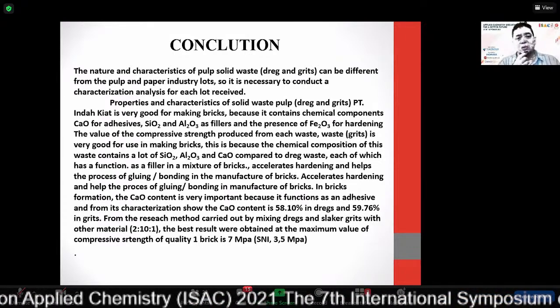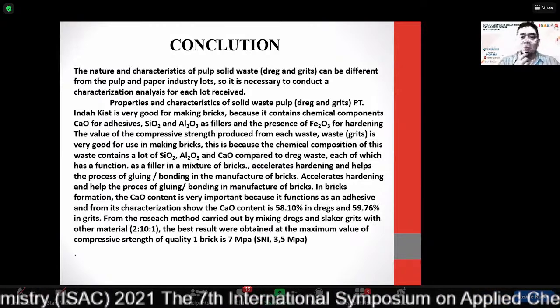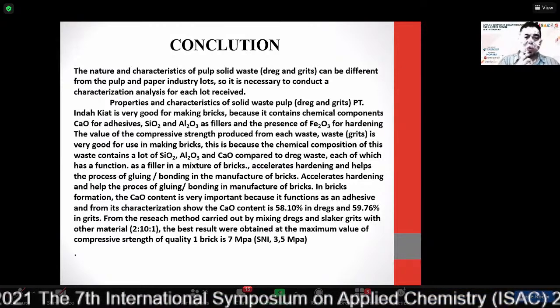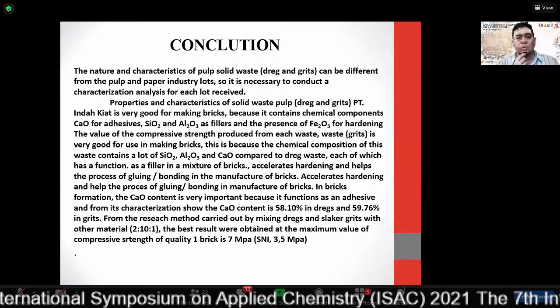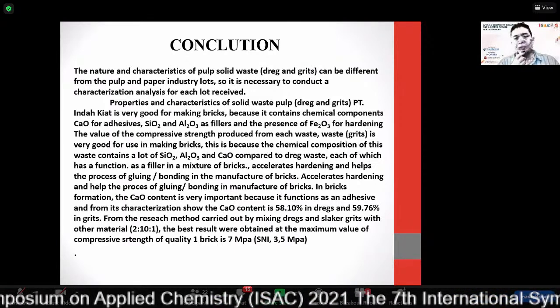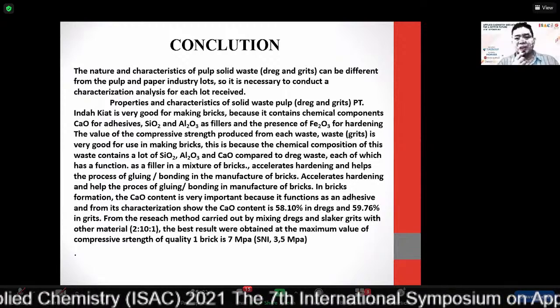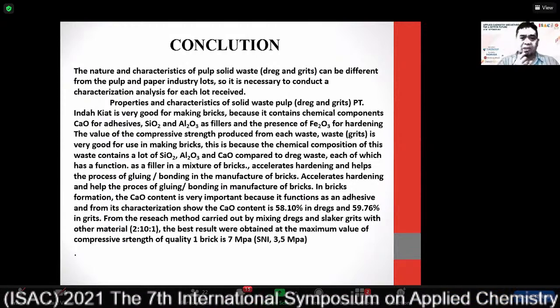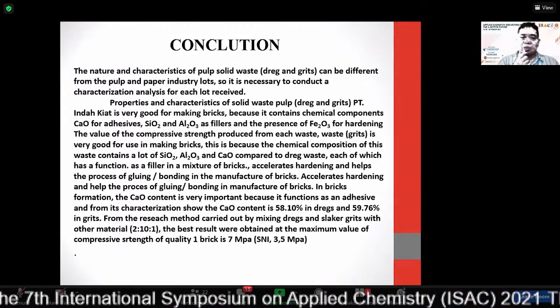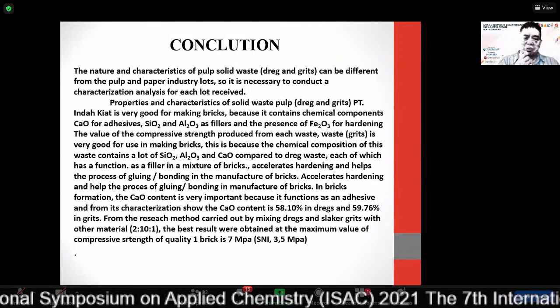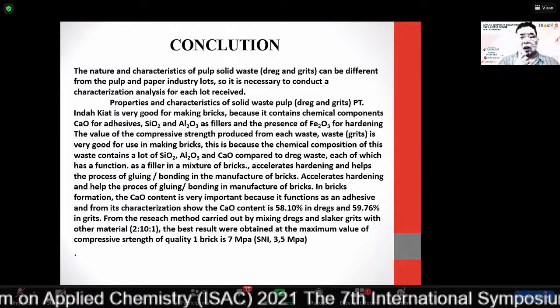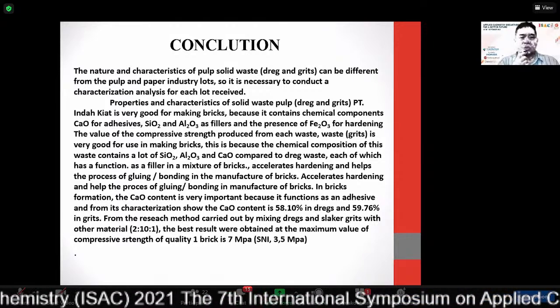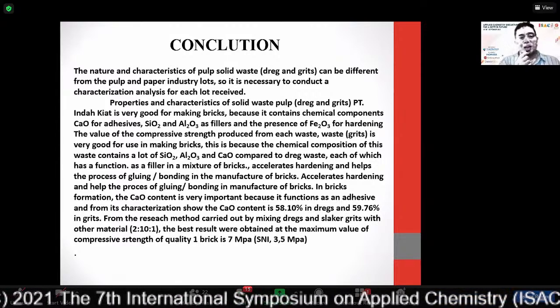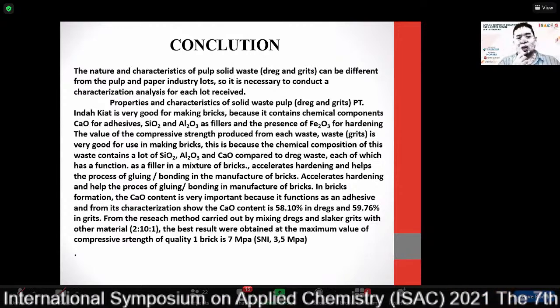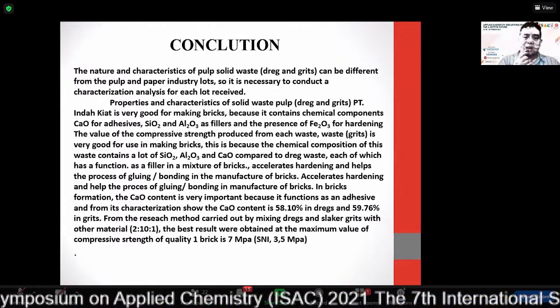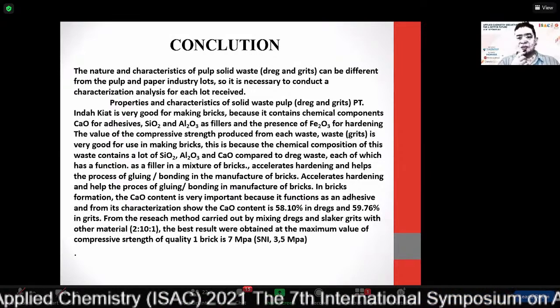PT Indah Kiat is very good for making bricks, because they contain chemical components like calcium oxide for adhesive, silicon oxide and aluminum oxide as a filler, and the presence of ferro oxide for hardening. The value of compressive strength produced from this waste, especially waste grit, is very good for use in making brick. This is because the chemical composition of this waste contains a lot of silica oxide, aluminum oxide, calcium oxide, compared to the dreg waste, like the table in the result.